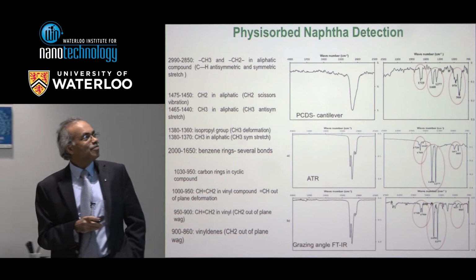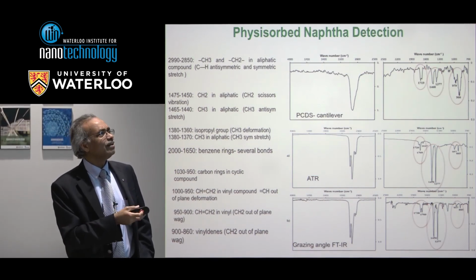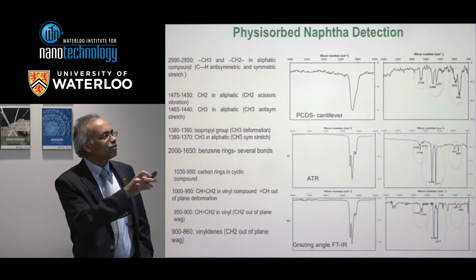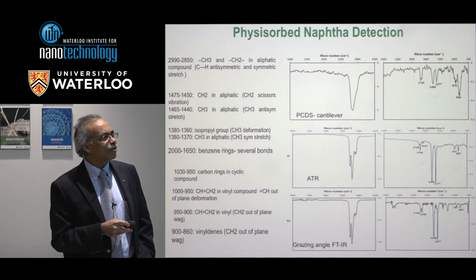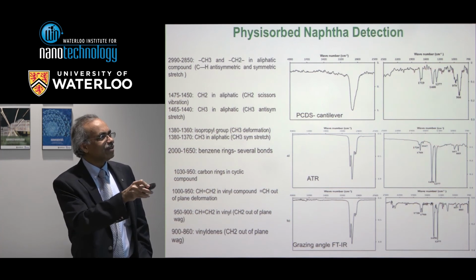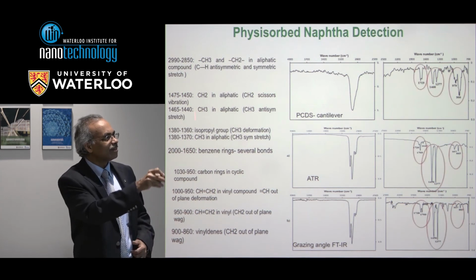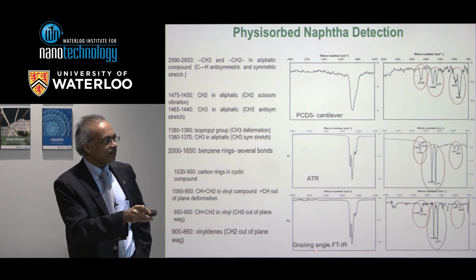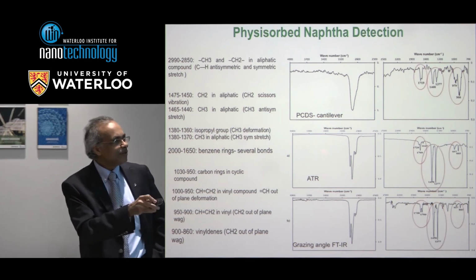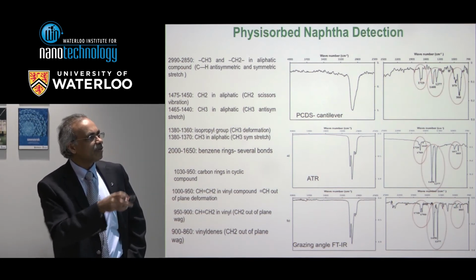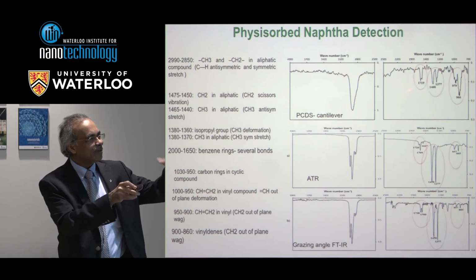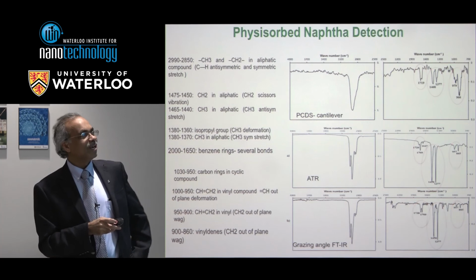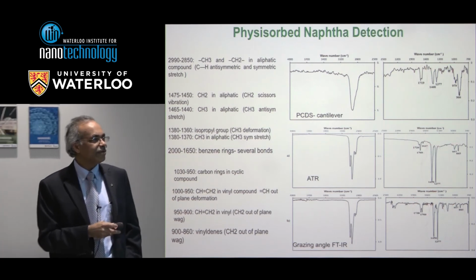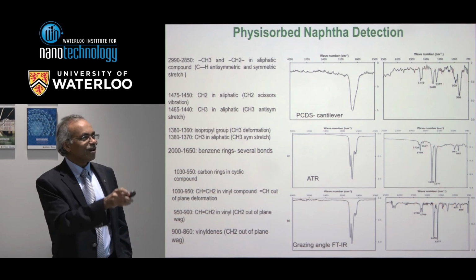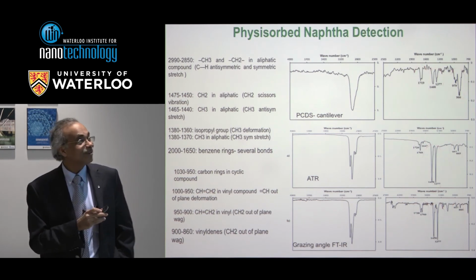So we thought we will put some naphtha on a bimetallic cantilever. So it's a picogram amount of naphtha adsorbed on the cantilever, and you are shining infrared 2 to 14 micron, and you can see all the peaks, molecular vibration as identified here. And this is the ATR, and this is the grazing angle FTIR. And you need a milligram amount of material here, while you need a picogram amount of material on a cantilever based upon the known Beer-Lambert principle, basically non-radiative decay. This is counting photons. And look at this, the signals are amazingly good actually.